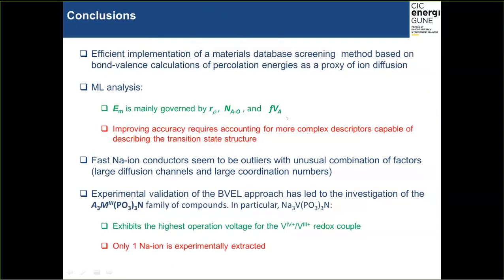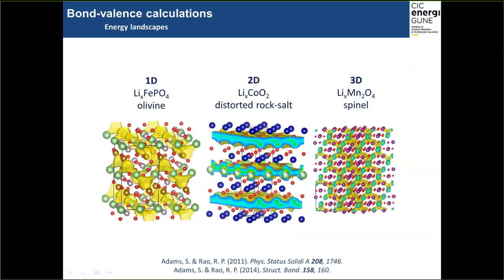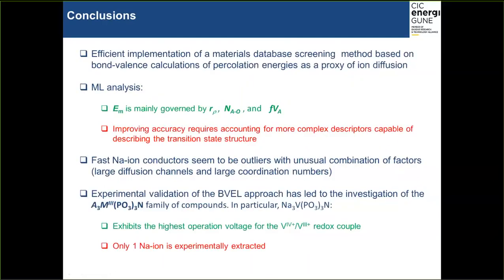So, with this, I come to the conclusions. Basically, I have shown you that we have scanned thousands of lithium and sodium compounds of the ICSD database. A machine learning analysis reveals that the migration energy is mainly determined by the bottleneck, the coordination polyhedron, and volume fraction of the mobile species. However, our machine learning predictions are not accurate enough to yield quantitative accuracy. And improving the accuracy will require accounting for more complex descriptors capable of describing the transition state structure.